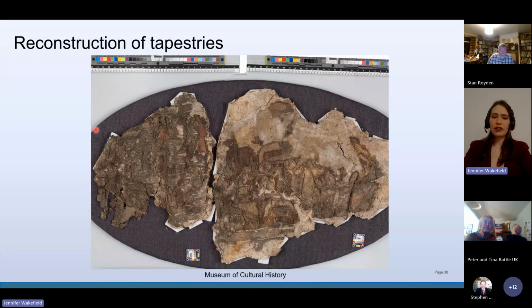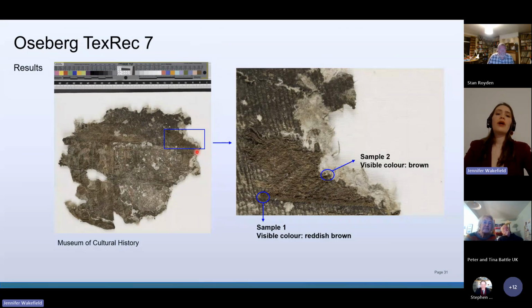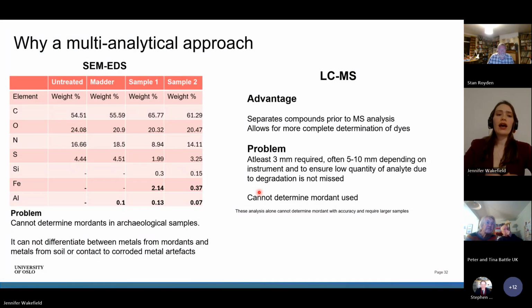So I wanted to zoom in on this a little bit more so you can see these figures and the different colors. The example that we're using to start with is this TEXREC 7. So for this particular one, we took two samples, one from this reddish brown thread here, and one from a more brown color to look at the two colors that were within this border. And we started with SEM-EDS.